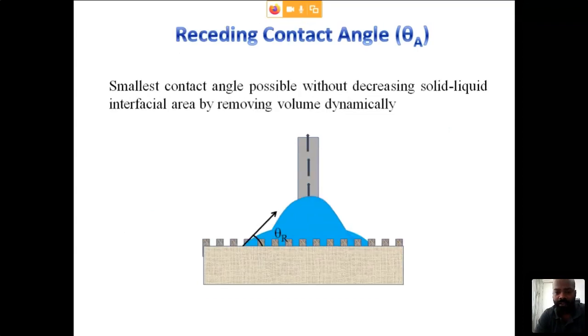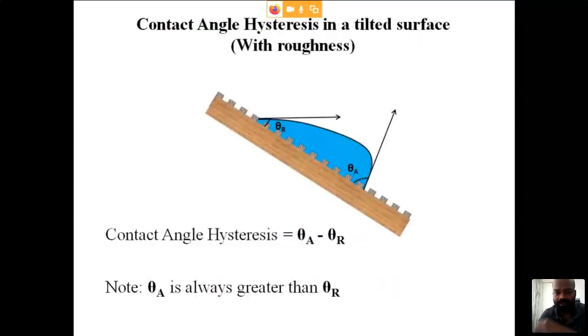I'll try to explain it using this. If there is a droplet which is sliding on an inclined surface, you can see that the front edge will have the higher angle as compared to the back edge. So this analogy we can use, and the difference in this angle is called contact angle hysteresis.